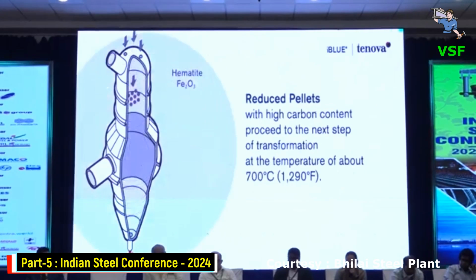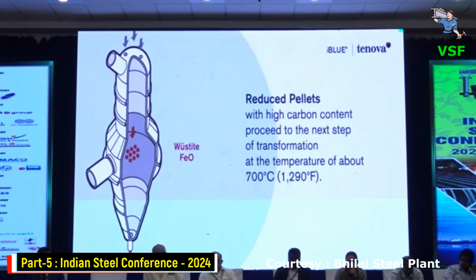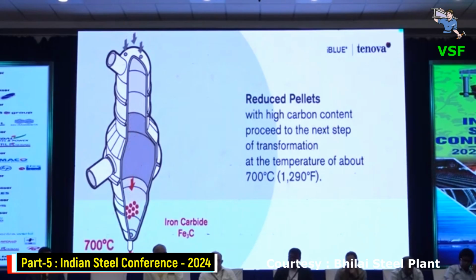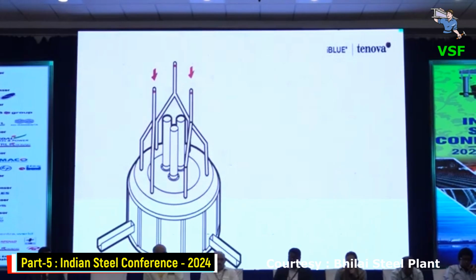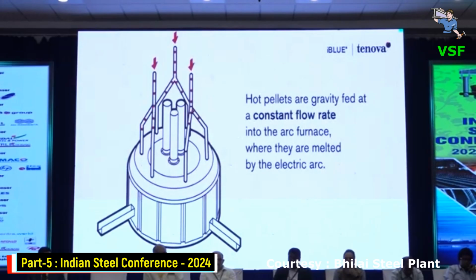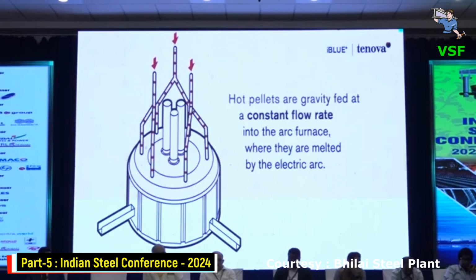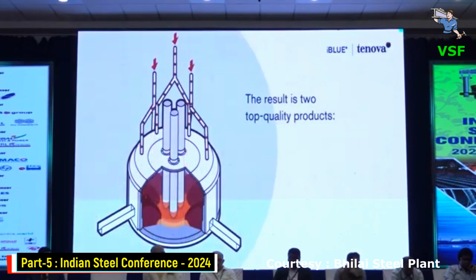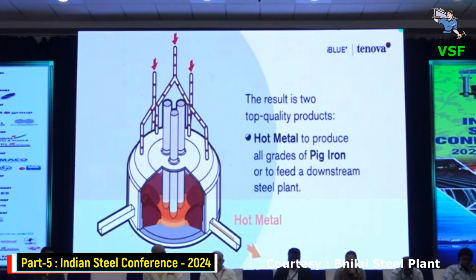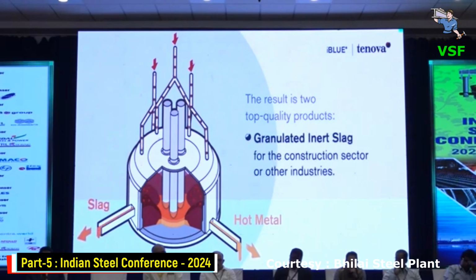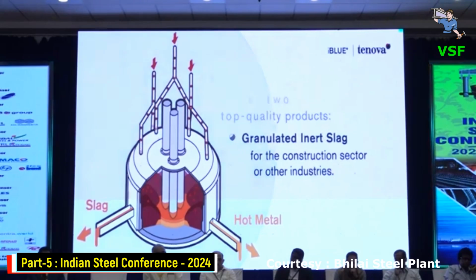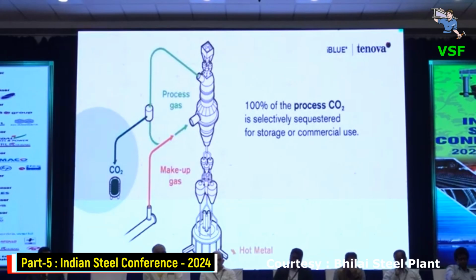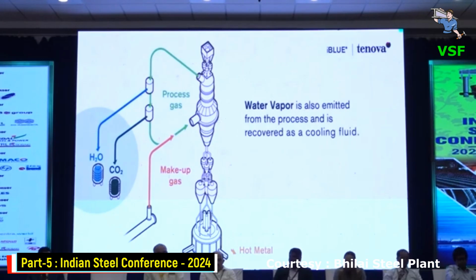Reduced pellets with high carbon content proceed to the next step of transformation at the temperature of about 700 degrees Celsius. Hot pellets are gravity fed at a constant flow rate into the arc furnace, where they are melted by the electric arc. The result is two top quality products: hot metal to produce all grades of pig iron or to feed a downstream steel plant, and granulated inert slag for the construction sector or other industries. 100% of the processed CO2 is selectively sequestered for storage or commercial use. Water vapor is also emitted from the process and is recovered as a cooling fluid.